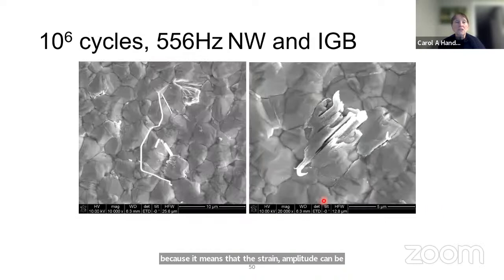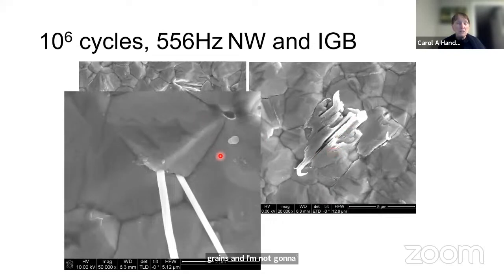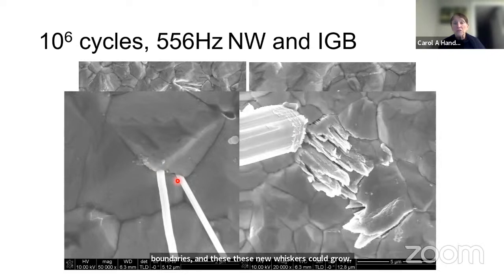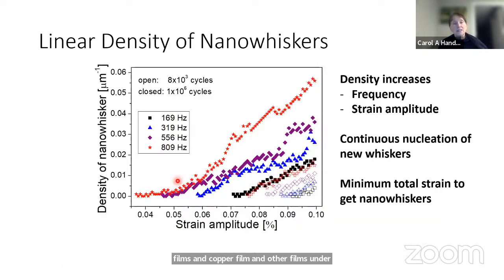So what we saw was tin whisker formation. We saw breakup of grains, and I'm not going to go into much detail. These instead of the original grains forming whiskers, we nucleated new whiskers along the grain boundaries, and these new whiskers could grow hundreds of microns in a very short time. And here are breakups of grains, and these have been seen in aluminum films and copper film and other films under different stress conditions.